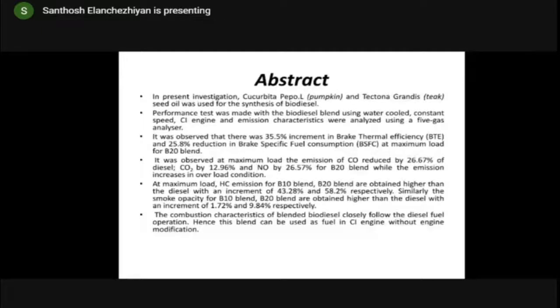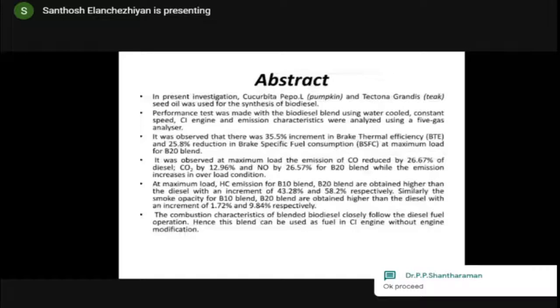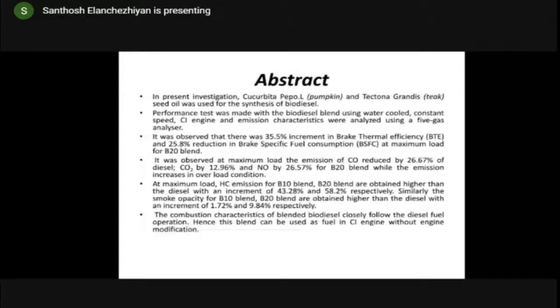Abstract. In this presentation, Cucurbita Pepo L, pumpkin and teak seed oil are used to synthesize biodiesel. Performance tests were made with the biodiesel blend using a water cooled CI engine, along with emission characteristic analysis. It is observed that there was a 35.5% increment in brake thermal efficiency and a 25.8% reduction in brake specific fuel consumption at a maximum load of B20 blend.